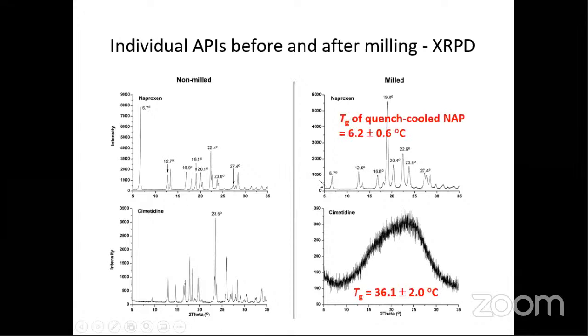We also used DSC to figure out the Tg of these compounds. The Tg of cimetidine is 36, and for naproxen it's super low. This is why we can't use milling to prepare amorphous naproxen - because the Tg is super low. Usually for these compounds you cannot use milling to prepare amorphous material.